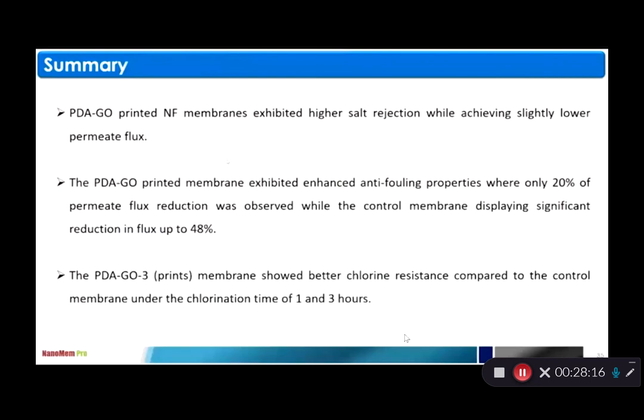So we can also summarize that the PDA printed nanofiltration membrane exhibited higher salt rejection while achieving a slightly lower permeate flux. The PDA GO printed membrane exhibited enhanced anti-fouling properties. And the PDA GO3 membrane showed better chlorine resistance compared to the control membrane.